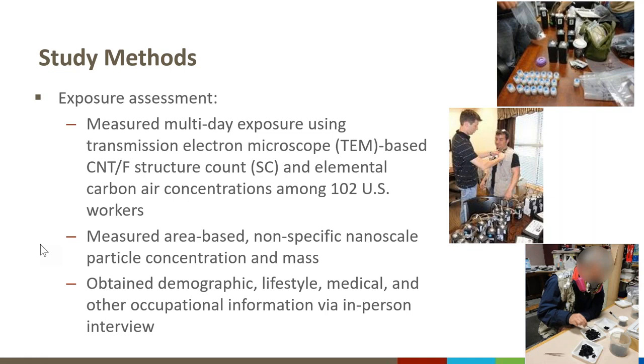We also measured area-based non-specific nanoscale particle concentration and mass. So that was particle number concentration and mass. And these were measured using a suite of direct reading instruments. The reason that we collected these area samples was to understand the ambient ultrafine particle concentrations within these workplaces that differentiated mostly at times with the actual carbon nanotube and nanofiber exposure. And it was also used as a confounder in our analysis.